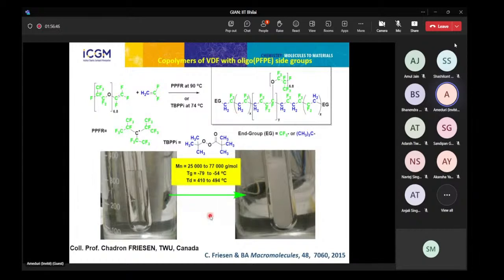So by NMR, of course, because these were not possible to inject by size exclusion chromatography, it was possible to measure the molecular weight by the end group, because the end group in the presence of this PFPE was a CF3. And in this case, we have a nice label, as I showed in the beginning, of the signals at -61 ppm, and knowing all the signals of the monomer and of VDF, it was possible both to determine the content of VDF, the content of perfluoropolyether, and the molecular weight.